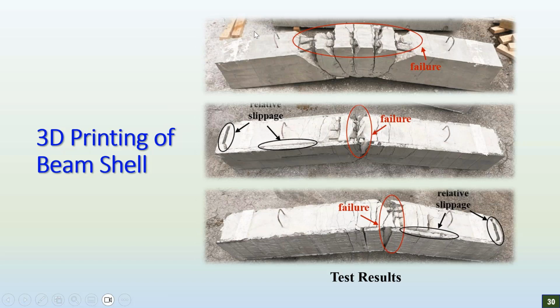So this is basically the tension surface of all three tested specimens. Again, for the concrete specimen, we can see a lot of distributed cracks and the failure pattern on top. And in the middle, this is the cast in place specimen. Again, it had one large crack in the middle, and this is the relative slippage between the concrete and the outside shell, which can be observed because there were no mechanical connectors in this specimen. And at the bottom, we can see the 3D printed specimen. Similar behavior was shown in the 3D printed specimen. The same kind of relative slippage was observed, and the failure pattern was also the same as the cast in place specimen.